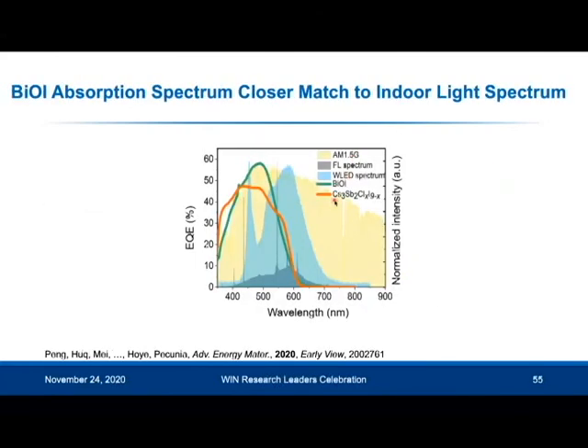Now, I mentioned earlier that bismuth oxyiodide has a band gap of 1.9 electron volts. And you can see the external quantum efficiency spectrum, which shows you the fraction of light at different wavelengths which are converted to electrons that are collected. And that's given by this green line here for bismuth oxyiodide. And you can see that this yellow region here, that's the solar spectrum, and there's lots of infrared light. I'll quickly wrap up. So there's lots of light which won't get absorbed.